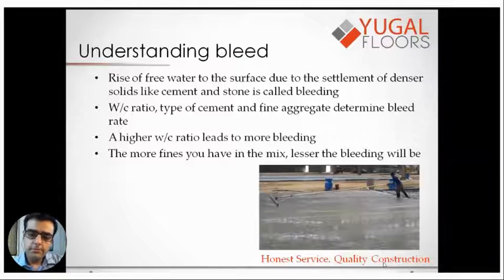So it is obvious, but it is important to state here that in a concrete mix, the density of water is the lowest among all components, so it is natural for it to rise up. And not just water cement ratio, but the type of cement and also the type of fine aggregate and percentage of fine aggregate determine bleed rate. It is obvious that a higher water cement ratio leads to more bleeding, and the more fines you have in the mix, the lesser the bleeding will be. The photograph shows you bleed. If you look, you can see a little shimmer on the floor. That is the water that has come and sat on top.